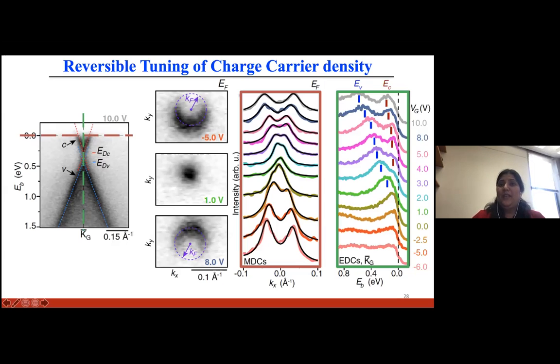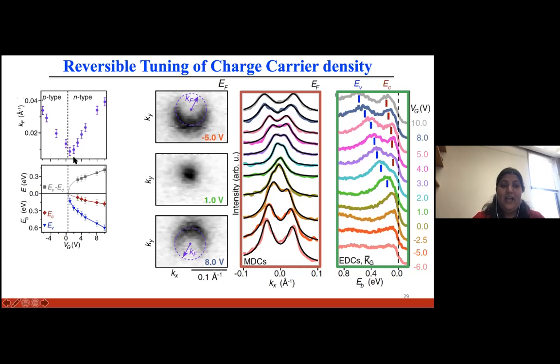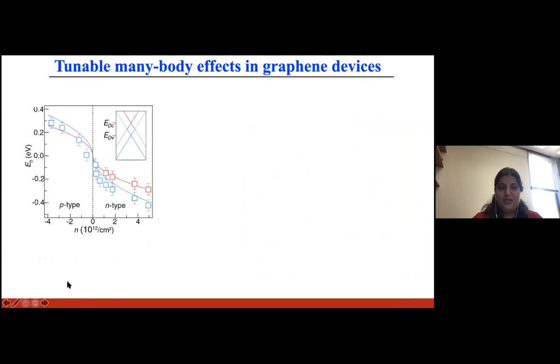And so what we can do is plot this radius Kf and these two peaks as a function of the gate voltage, which I'm showing here. And we can also plot the separation between these two crossings, which are these gray data points. What is interesting is that this doping-dependent separation of the Dirac crossings shows us that many-body interactions are contained in the photohole spectral function. And in order to investigate further how these many-body interactions depend on doping in our device, we can fit these MDCs much better and extract a more precise estimate of the binding energies of the Dirac crossings. And then we can plot it as a function of the charge carrier density by using this relationship. And this is what I'm showing here.